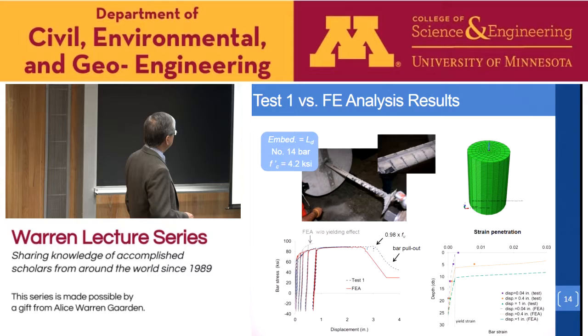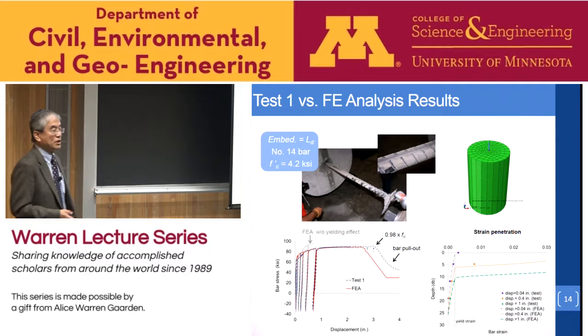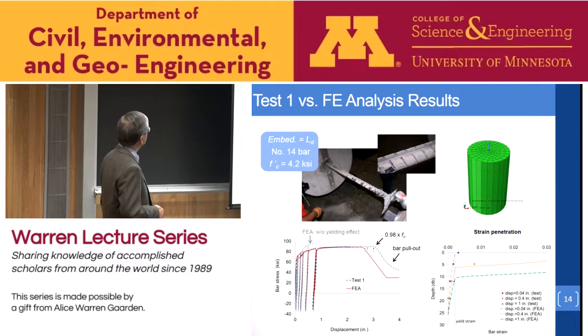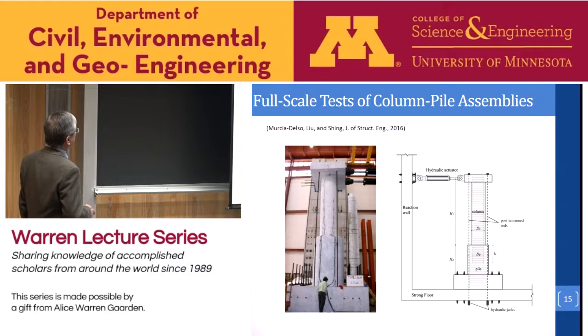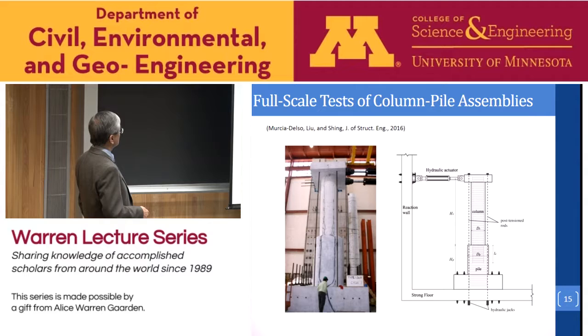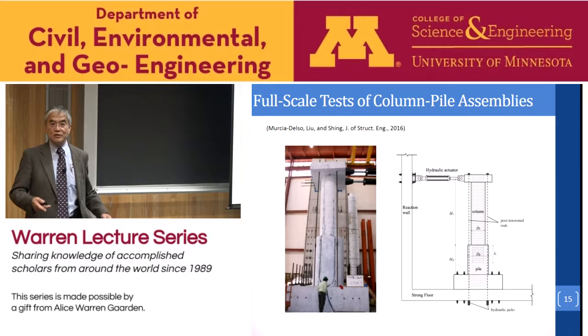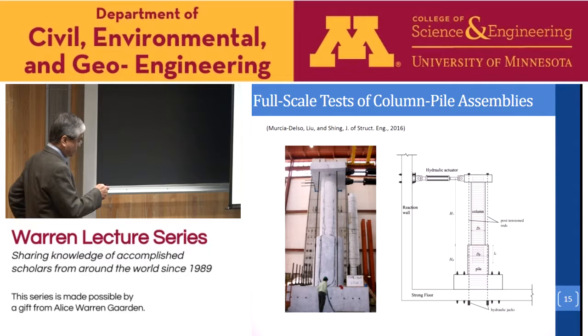This also shows the strain developed along the bar, okay, along the depth of the embedment length. You can see the model also captured the experimentally measured strain relatively well, okay, considering this is a cyclic testing. So finally, with this model, we did some numerical studies, and with our numerical results, we designed 4 test specimens, okay? The full-scale specimens. In all those specimens, we terminate all the column reinforcement at one point. We didn't use a staggered approach because the analysis showed that that's sufficient. So this shows the design of 4 specimens, okay?